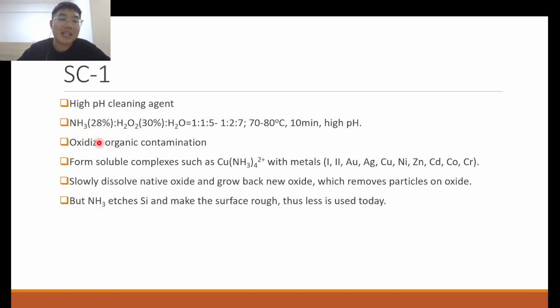Sometimes they write it as NH4OH, to represent that ammonia is aqueous. In the aqueous state, it's ionized, it's dissociated. So the purpose is that this is able to oxidize organic contamination, because of hydrogen peroxide. And in addition to that, the presence of ammonia is able to form soluble ammonia complexes, such as this one, Cu(NH3)4 2+, with certain metals, especially transition metals like copper. They actually form soluble ammonia complexes.